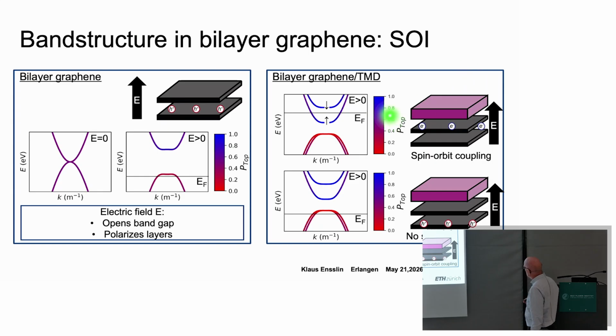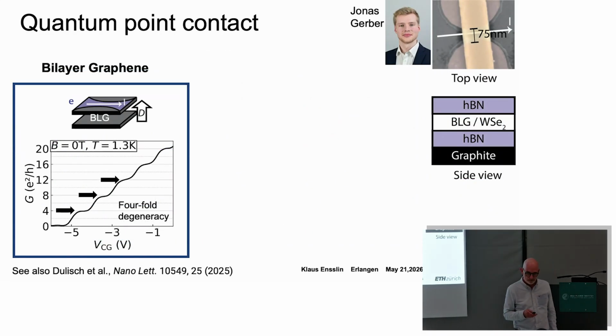And now, because of your gate voltages, you can park your electrons in the graphene layer next to the TMD or away from the TMD. If they are away from the TMD, they don't feel the TMD anymore. And so just by moving your electrons by gate voltages by one layer, you switch from strong spin-orbit interactions to weak spin-orbit interactions. You know, within the microscopic description, what is happening? How do you turn off and on the spin-orbit coupling? So there are DFT calculations that have shown that it's basically the molybdenum atoms. They are, in molybdenum disulfide, the heavy atoms. They are responsible for the strong spin-orbit interaction in the TMDs. And these orbitals penetrate into the graphene.